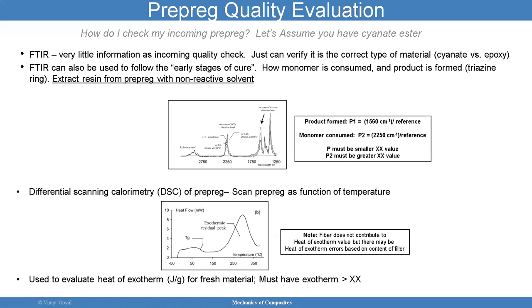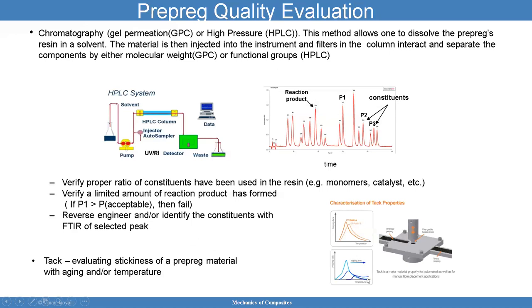So really it is the resin driving these things, which makes sense because the resin is there to glue things together. So that's, again, when we're evaluating prepreg quality, we're looking at things that could affect the ability to glue things together. And so we use the heat of exotherm and make sure that degree of exotherm is greater than a particular value that may be provided by a supplier to make sure it's good material.